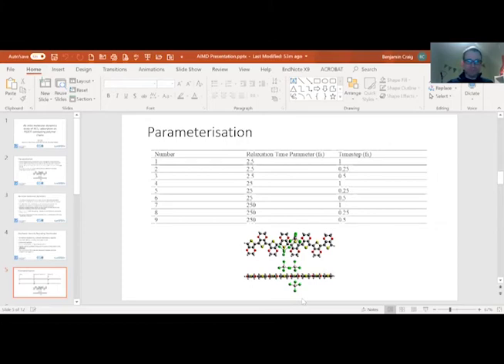Okay, so as you can see, you get some anions starting to move. One of these anions is starting to move site. One of the interesting things I discovered earlier on in the PhD was that these anions had a very strong preferred location over the sulfur atoms. And they wouldn't actually move from this unless they had a really high degree of Coulombic repulsion between the anions. So the fact that this anion is trying to move is indicative that this positioning of having two on either side of the